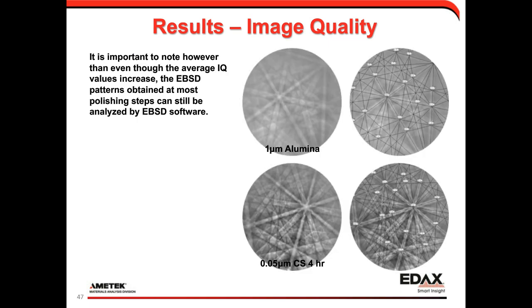But when we look at this, if we show that 1 micron pattern and we show our 4-hour colloidal silica pattern, sort of what we saw in the initial part of the presentation is both of these patterns are indexable. We can detect the bands and we can determine an orientation with high confidence. So what we want to know is what percentage of the points can we index at each step.